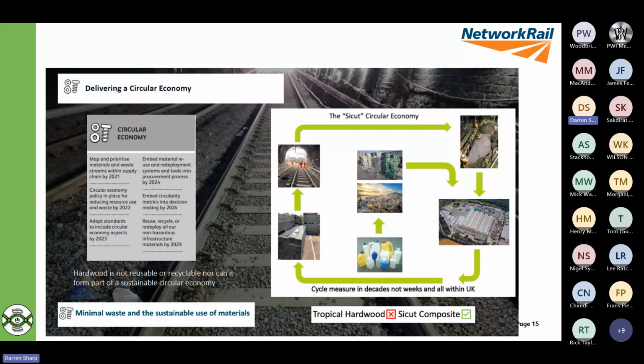Whereas with a plastic bottle, you're only looking at something like 6 months from start to finish once it's in the cycle, or in some cases 6 weeks. And then after about 6 cycles, it starts to deteriorate as well. So this is a lot larger loop, which means we get carbon locked in and embedded in for a lot longer time.